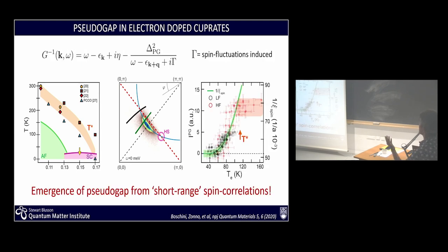And so this is the outcome. Here we have the intensity of the pseudo-gap. As we increase the electronic temperature, we see that the intensity at the so-called hot spots increases and eventually saturates. Now it's interesting to see where that happens. The saturation happens at a temperature which is actually T star for this particular system. It's a crossover, clearly.